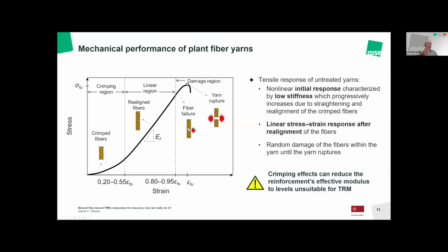This is a typical tensile test, and you will see that you have a very long piece of deformation before the stiffness will increase once you straighten the fibers. This is very nice. We would like to be on this part, okay? But before reaching this part, you have to accommodate this deformation, and this may be unsuitable inside the mortar matrix. So this is a serious problem that we have to handle.